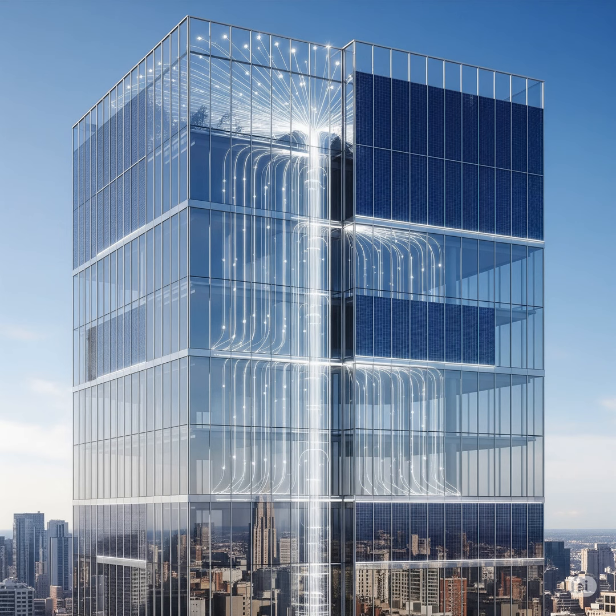Okay, progress. But were there still downsides? Oh, definitely. It wasn't perfect yet. For one, the initial versions needed to get quite hot, over 100 degrees Celsius, to make the switch. Oof, that's pretty hot for a window. Yeah, not ideal. And the efficiency was lower, only around 7% initially. Plus, there was an aesthetic issue. One expert called it a crucial factor for builders. Let me guess, it wasn't perfectly clear. Worse, it had a distinct reddish tint when it was opaque. Oh, yeah, I can see architects not loving that. A red window. Exactly. So still hurdles to overcome.